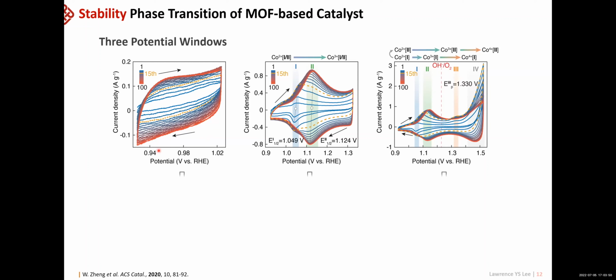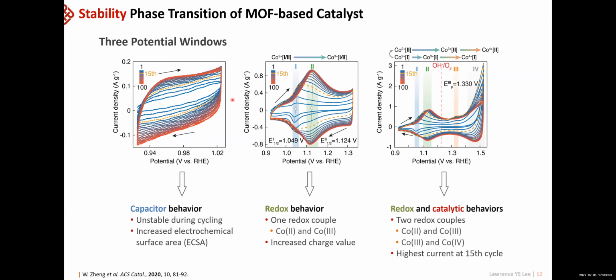As you can see from these CVs, they are quite different. When we scan at lower potential window, we only see the capacitor-like behaviors. But when we started to increase potential to 1.3, we see some redox behaviors, which corresponds to the conversion of the cobalt-2 species to cobalt-3 species. One thing interesting is that the peak position as we scan is actually shifting. Initially, it occurs at a lower potential, but at some point, we start to see both of them. And in the end of this 100 cycle, they move completely to the higher potentials, which indicates that there are two types of cobalt-2 species converting to two types of cobalt-3 species.